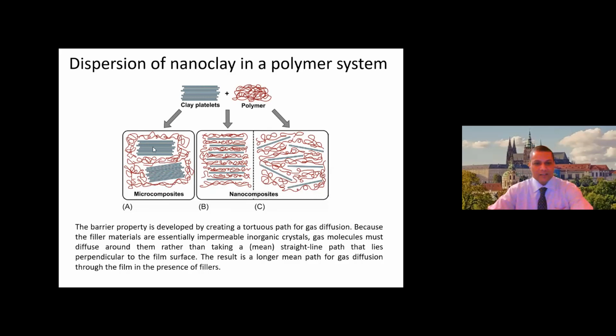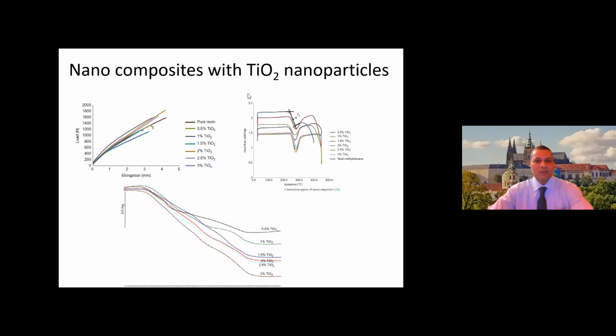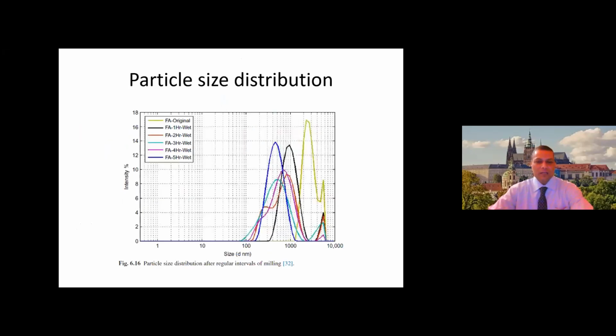Otherwise, these clusters or agglomerations, points of agglomeration, they rather act as stress concentration points, and that can be region of deteriorated mechanical property. In some of our research, we have used nanoparticles for reinforcement of composites, along with fabric-based reinforcement, and substantial improvement of mechanical property up to 7-8% in modulus and thermomechanical properties has been observed. It is not simple to obtain nano dimension in particle. It is necessary to have prolonged period of grinding.